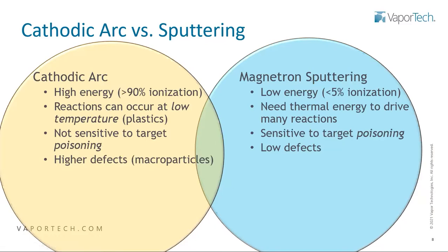The one drawback with cathodic arc is the amount of defects that are ejected from the process. Now, these are really small liquid droplets that occur because it's such a high energy process. The nice thing about decorative coatings is they're so thin that these macro particles really don't play a role. They're invisible. They don't have any real effects. But in contrast, magnetron sputtering has many fewer. It's not a no defect, but it has much fewer defects than from cathodic arc.